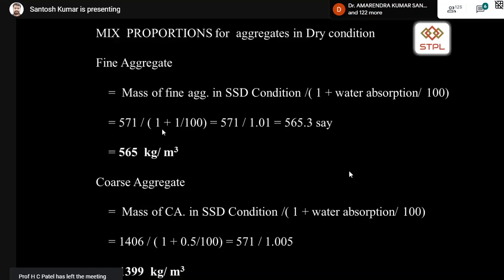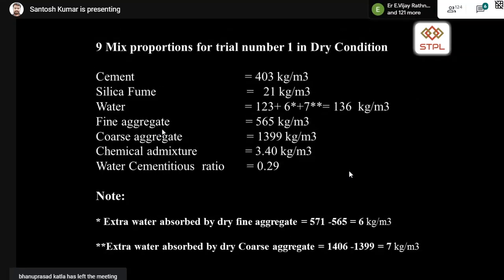In the same way for coarse aggregate, mass of coarse aggregate divided by 1 plus water absorption, considered as 0.5 for coarse aggregate, divided by 100, gives you 1399 kg per cubic meter. Whereas in SSD condition, it is 1406. So 1406 minus 1399, 7 kg is the additional water you add to make the aggregates become SSD. So if you calculate the proportions in dry conditions, the water is increased. Instead of 123, you are taking 136 kg. 6 kg you are adding extra water, which is absorbed by fine aggregate. From 571 minus 565 becomes 6.